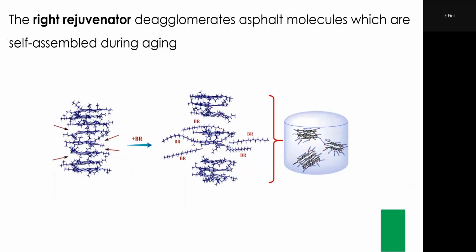The true rejuvenator, in our group's position, is that we need to deagglomerate the asphaltene aggregates, and deagglomeration is only possible with some of the molecules. Not every softener can break the agglomerates. So the rejuvenator has to have the capacity to break down these agglomerates by diffusing into the structure and then causing enough steric repulsion to push these aggregates away, and ultimately you get smaller aggregates. This is just a schematic, but I'll show you some of the simulation as well. So deagglomeration is the mechanism we think is leading to true rejuvenation.